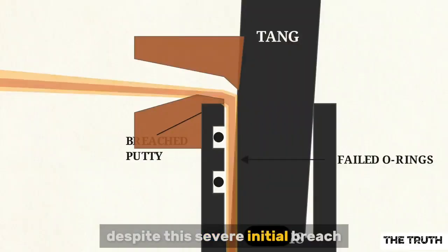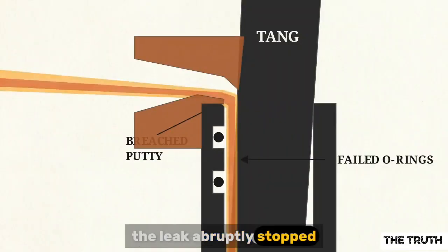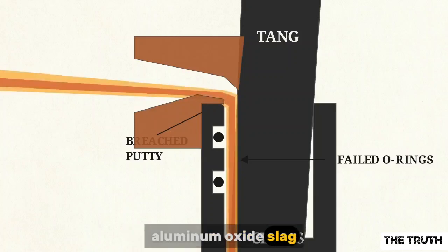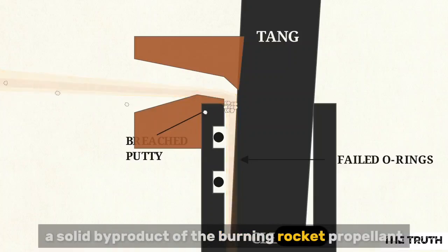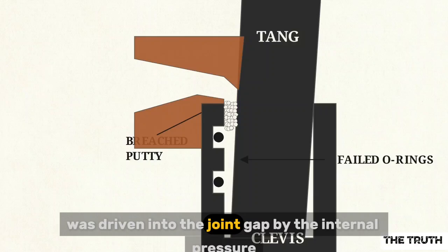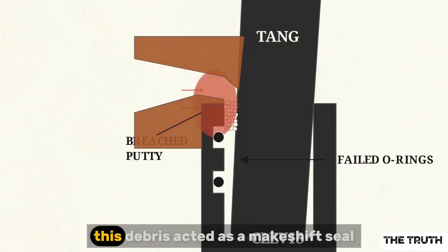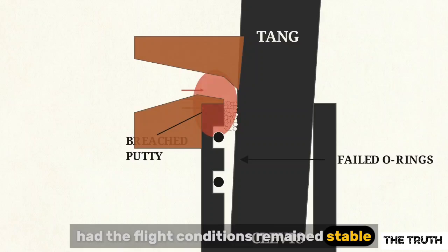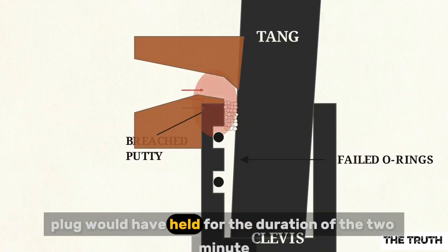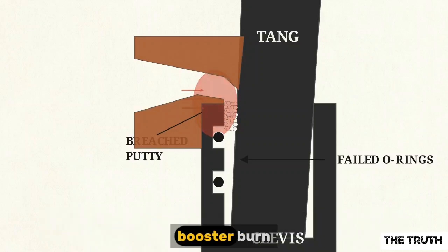Despite this severe initial breach, the leak abruptly stopped. Aluminum oxide slag, a solid byproduct of the burning rocket propellant, was driven into the joint gap by the internal pressure. This debris acted as a makeshift seal. Had the flight conditions remained stable, this slag plug would have held for the duration of the 2-minute booster burn.